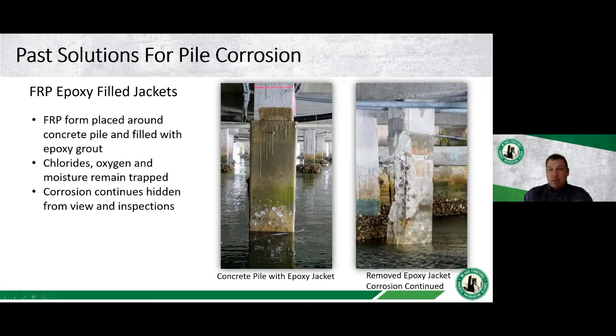The thought was that if we put this jacket around it with the epoxy, we could at least maybe choke off the corrosion and prevent it from occurring, but it actually continues underneath of the jacket. One thing to note is this jacket here that you're looking at is the actual jacket that was removed. There's all this corrosion occurring underneath of these stay-in-place jackets, and the corrosion isn't visible. So we were unaware of all the damage that was occurring to the reinforcing steel, or in this case, the pre-stressing strands within that pile.